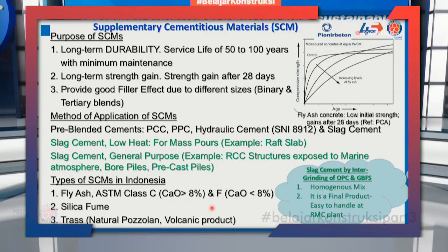Now, what is the effect of SCMs? SCMs not only provide you durability, they also give long-term strength. You can see in the graph here. In this graph, if I use more of fly ash, the initial strength will drop, but later on you see here, it exceeds your OPC. There's a long-term strength gain. That's the most critical thing for most of the elements. Whereas if you use 100% OPC, it forms a plateau and you do not find long-term strength increase. This is a major advantage of using SCMs.